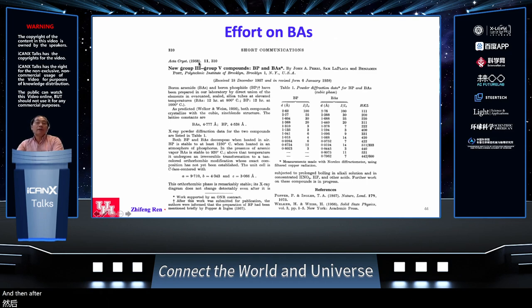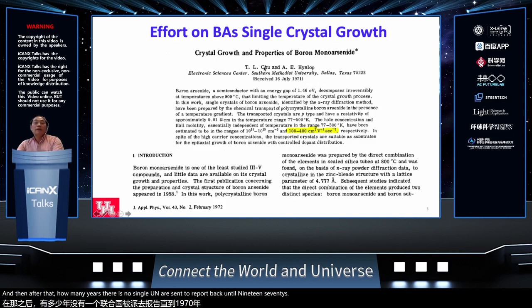After that, for many years there was not a single other report until the 1970s. They tried to make a single crystal; at that time they were pursuing III-V crystals. They looked at the band gap, found 1.46 eV, and also found the mobility somewhere between 100 and 400. And the thermal conductivity was very low. They were not even measuring thermal conductivity, because their intention was to study the semiconducting behavior of this material. After that, there is no other paper about experimental work on this material.